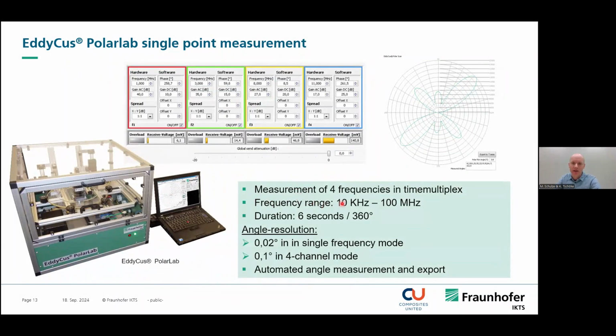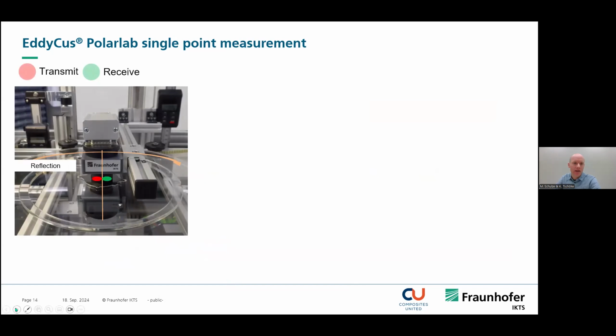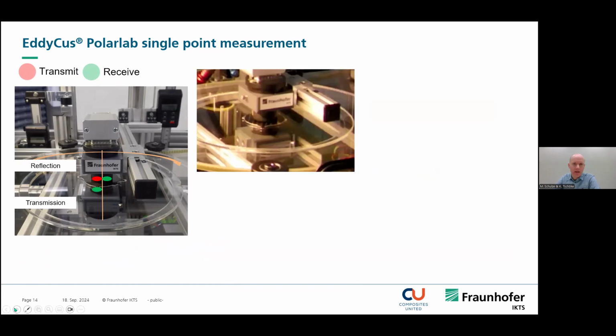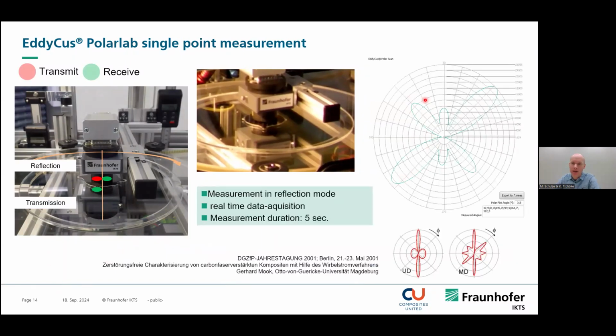It works at frequencies from 10 kilohertz to 100 megahertz. We can acquire 4 frequencies in parallel. It only takes 6 seconds and has a high accuracy. It can work in so-called reflection mode and also in transmission mode. Here we see an example of how it works. So the probe rotates, and in parallel the polar diagram is acquired, and you can see here the analyzed fiber angle of this small specimen. So we have 3 fiber orientations, and there's a little displacement in the fiber.